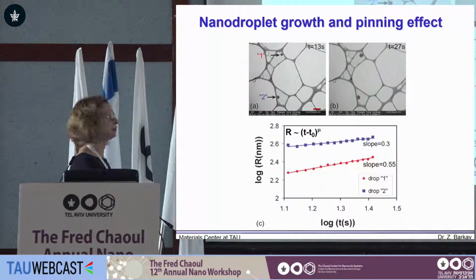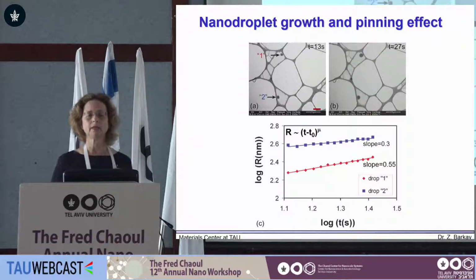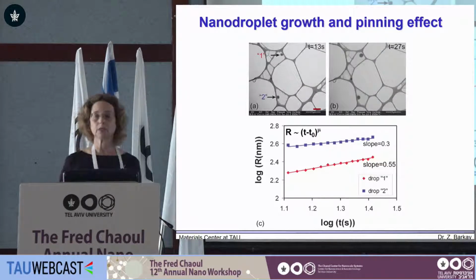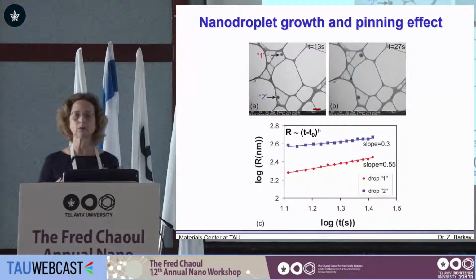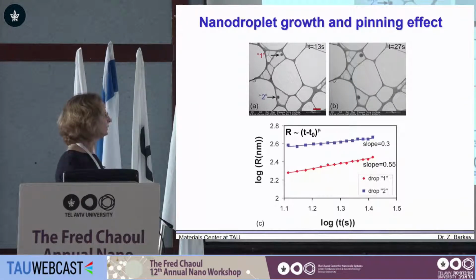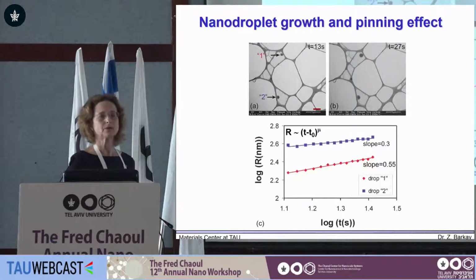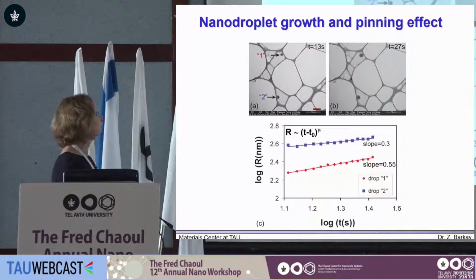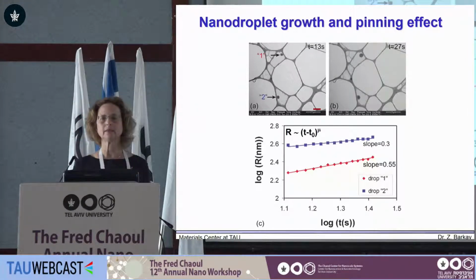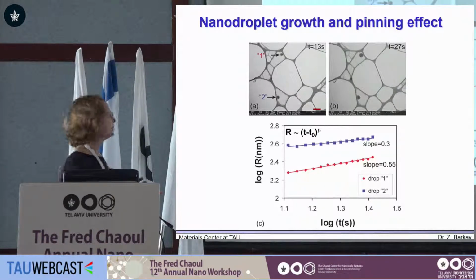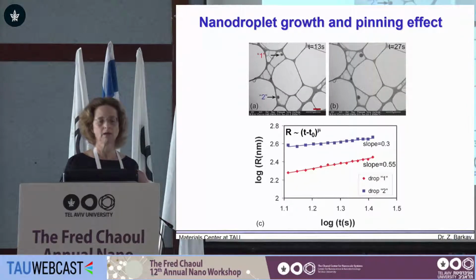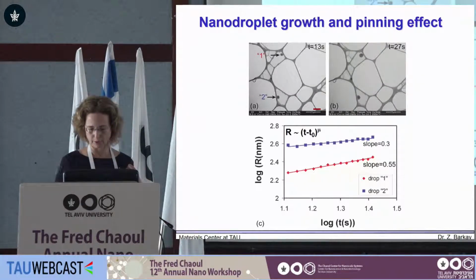What we find here is the fit parameter is around half or below, and it fits the growth that comes from vapor coming to the perimeter of the drop. But what is also interesting is that we have two parameters, meaning there is something additional in the system that is not consistent, and this is actually the pinning effect. So now we can understand the stability is not only by the curvature and shape of the drop, but also by the pinning effect to certain sides in the specific configuration.